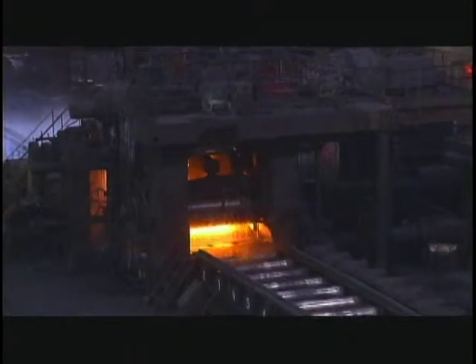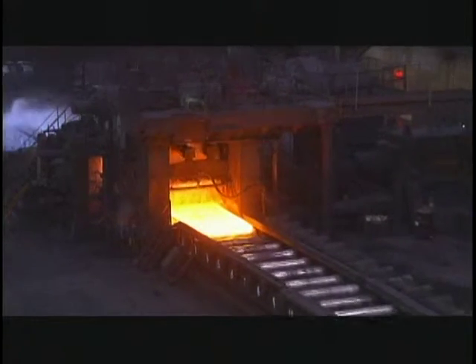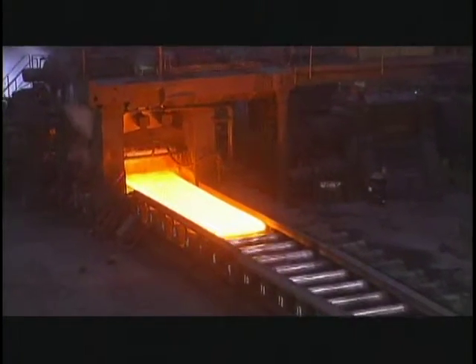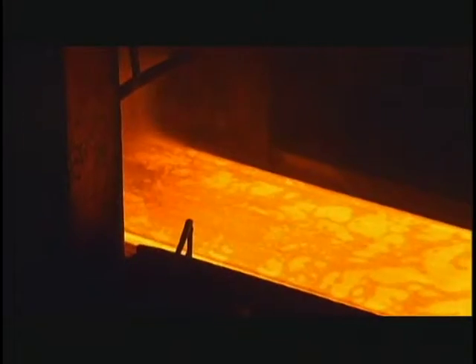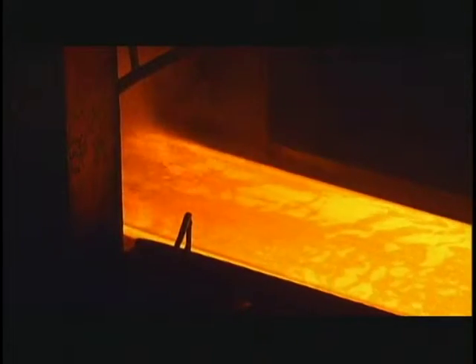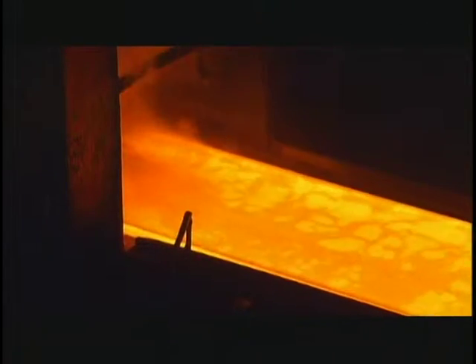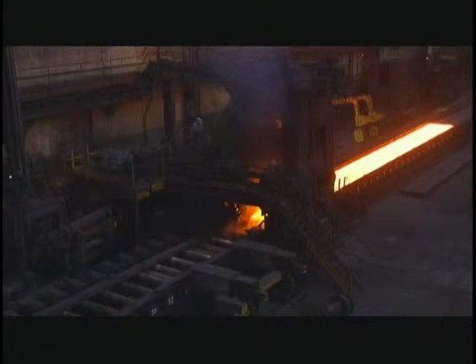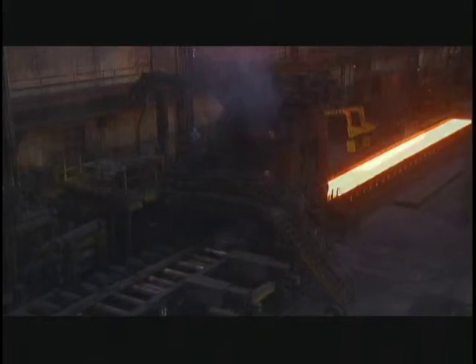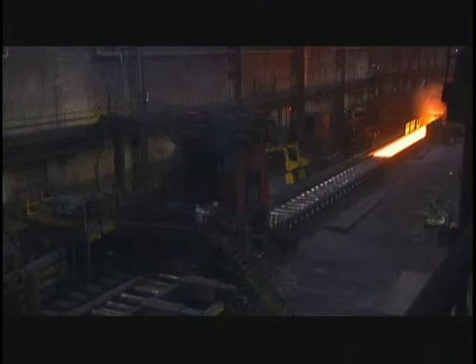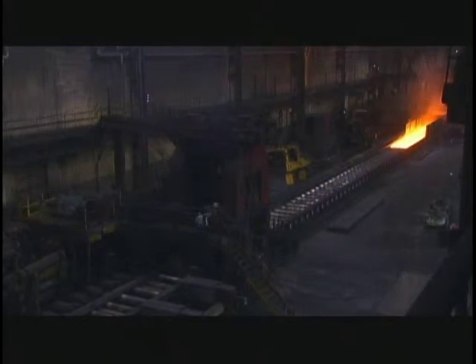This is the roughing mill area. We'll be receiving the bar from the furnaces after the discharge. First thing we'll go through is a vertical scale breaker, which loosens the scale, the impurities formed from oxygen from heating the slab in the furnace. After the scale is loose, it'll go through a series of high-pressure descales to knock the scale off. Then it'll go through R1, R2, R3, and then R4, and then we'll have another descale at R5 to get rid of everything before the finishing mill receives it out of R5, which would be 1.3 inches by the time it goes through R5.